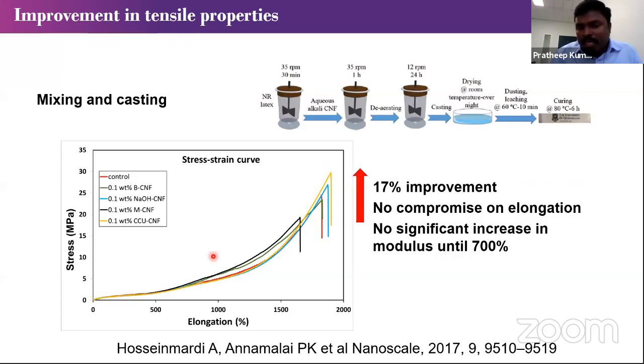But we did not stiffen this material, because we want that flexibility. So you shouldn't see the increase over here. If you see an increase in this region, that means you are stiffening the material, and you don't want to do that. You just want to increase the strength, which we could achieve with these long, thin, flexible nanofibers.